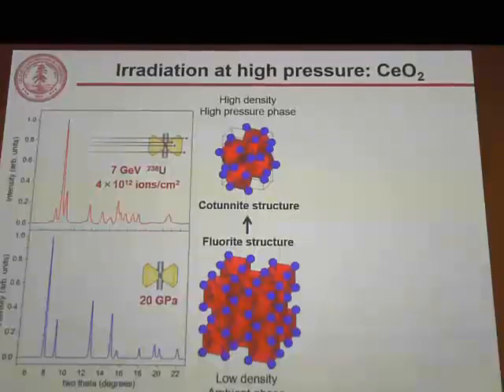So what I did here is I took cerium dioxide, pressurized it to 20 gigapascals, and we see from the XRD data shown on the bottom that the fluorite structure is still maintained at this pressure. If we then irradiate this material while it's at pressure by injecting swift heavy ions into our diamond anvil cell, we see in the upper XRD a clear transformation to a new high density cotunnite phase. So it's no longer the fluorite structure, it's now cotunnite.